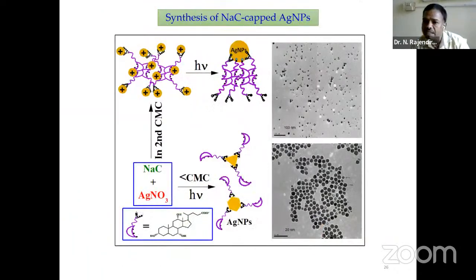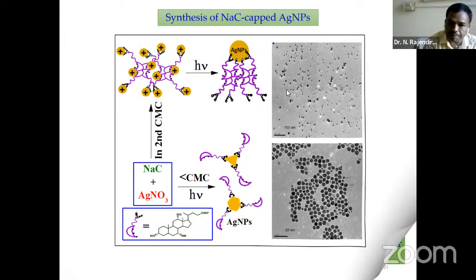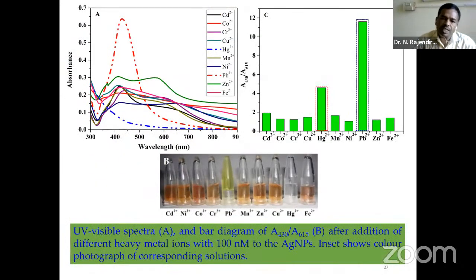This is the schematic representation of the mechanism of how sodium cholate reduces the silver salt below and above the CMC. Below the CMC, the formed particles are mostly anisotropic in nature, whereas above the CMC, the particles are spherical in shape. So after the synthesis, the silver nanoparticles can be used for the colorimetric detection of metal ions.